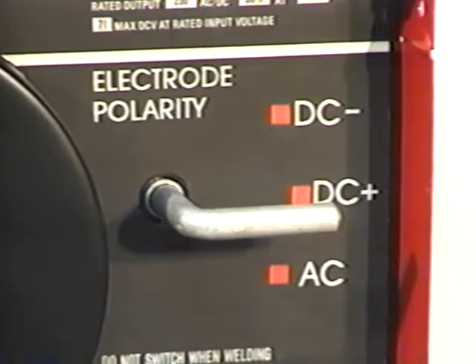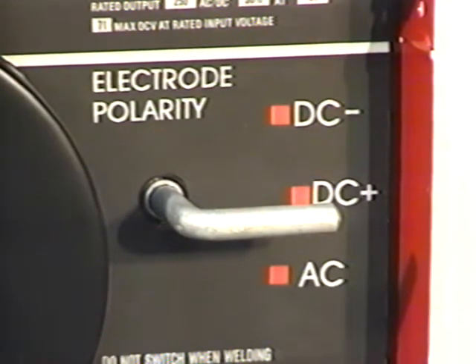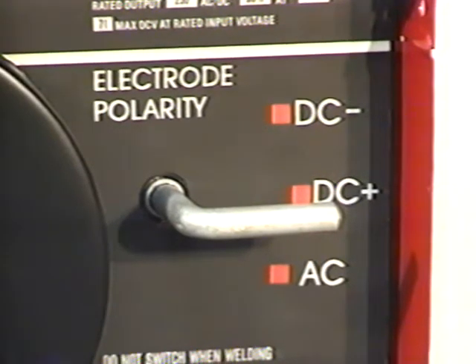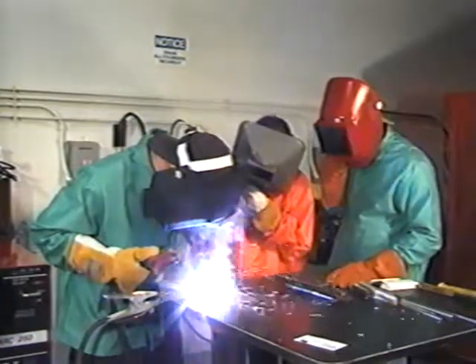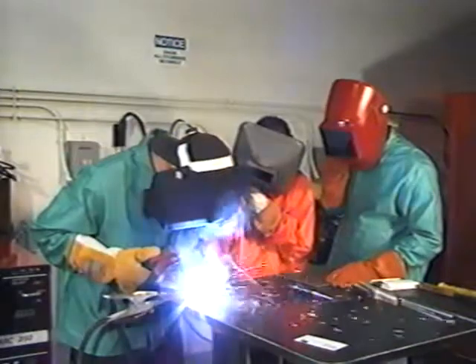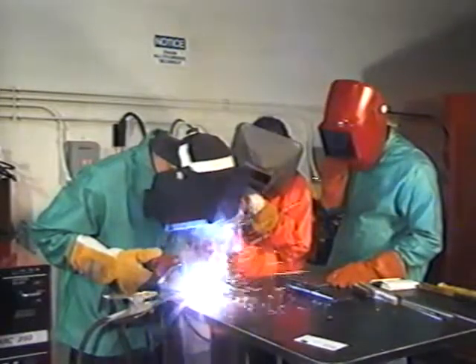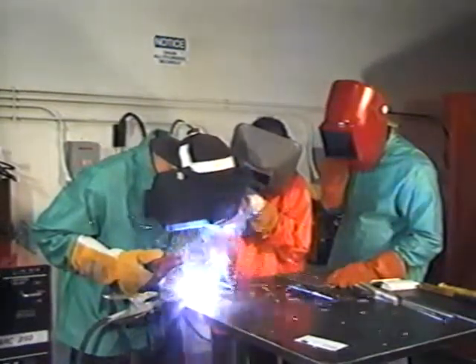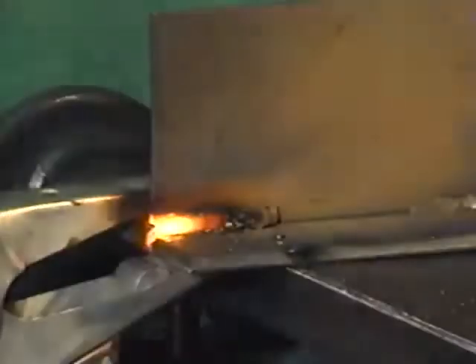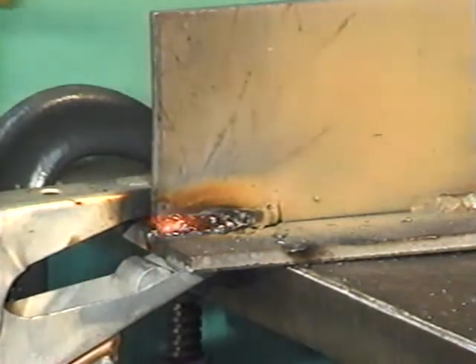Direct current welding holds another problem for the welder. The arc created with a direct current machine is influenced by the extreme magnetic field made by the current passing through the electrode and the base metal. This deflection of the arc from a straight path is called arc blow. It is most evident at the end of a joint or corner. The fluctuating magnetic field tends to draw the filler metal out of the joint. Repositioning the ground lead and using a shorter arc sometimes helps to solve this problem.